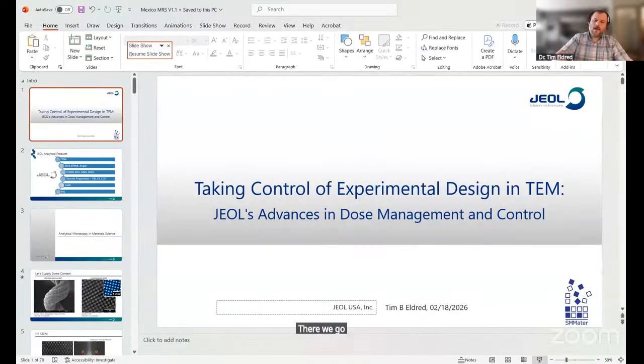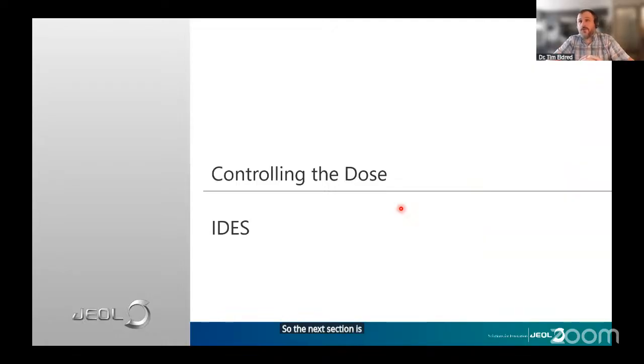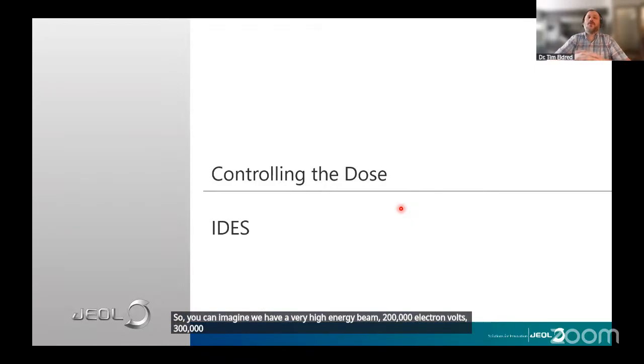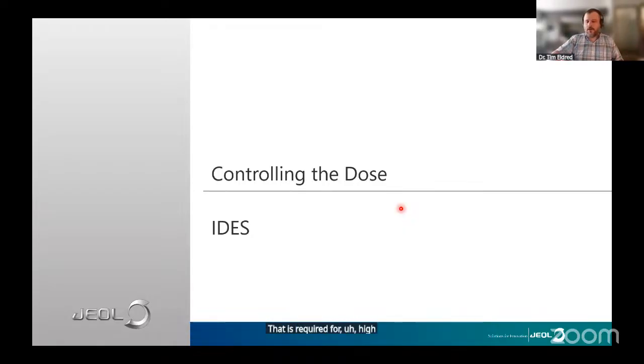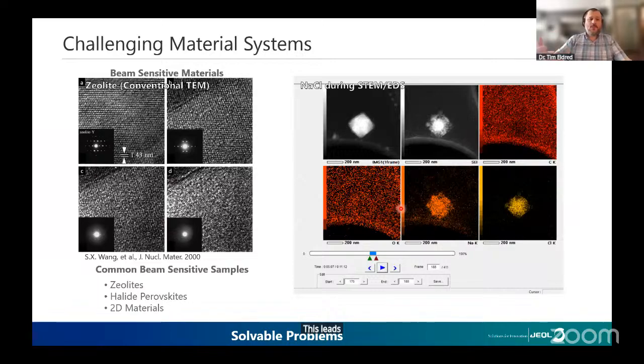There we go. So the next section is talking about dose control. You can imagine we have a very high energy beam, 200,000 electron volts, 300,000 electron volts, that is required for high-end atomic resolution imaging. This leads to challenges with beam-sensitive materials. Kind of the classic example is zeolites, where as you image them, they go from crystalline to fully amorphous. But other samples that you might not think of as heavily beam sensitive, sodium chloride. Over the course of doing elemental analysis, it goes from a crystalline cube to fully degraded and broken down.